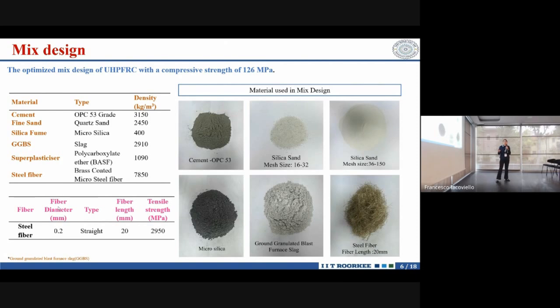So these are the materials that are used to develop this mix. Usually in UHPC the requirement for cementitious content is very high. So in order to reduce the consumption of cement, we have replaced the cement with other cementitious materials like microsilica and ground granulated blast furnace slag in different proportions, so that these microfine particles will fit in the micropores and densify the mix, and without compromising its strength, they will fill the pores. Additionally, we have used fine silica sand in different mesh sizes to again give a dense packing to the structure. And we have used straight steel fibers of aspect ratio 100, with 20 mm length and 0.2 mm diameter.